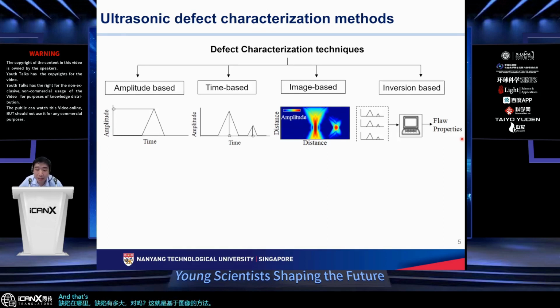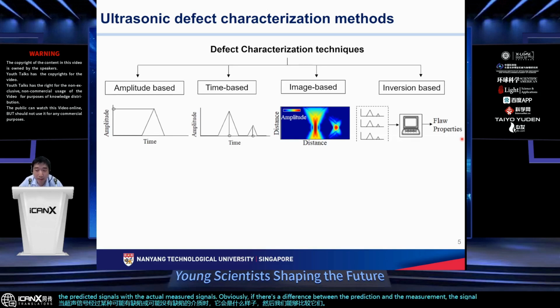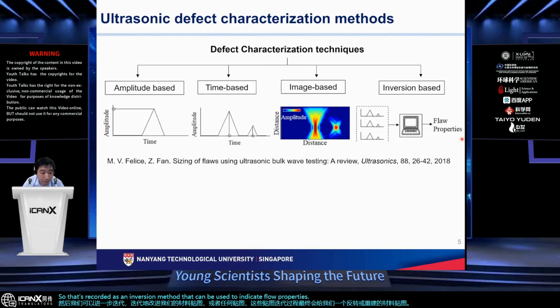And the last method we want to mention is the inversion-based method. So if you have a structure with certain defects, we can create a forward model that's able to predict what the ultrasound signal would look like when it goes through a medium that may or may not have a defect. Then we compare the predicted signals with the actual measured signals. Obviously, if there's a difference between the prediction and the measurement, the signals won't agree with each other. Then we can iteratively improve our material map. This iterative process will, in the end, give us an inverted or reconstructed material map, right? So we call it an inversion method, which can be used to indicate flaw properties. So that's something in general.